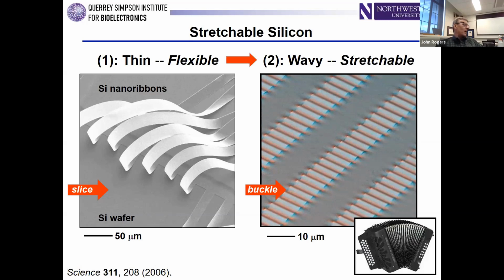Still silicon, it still offers the same electronic properties, can be thick enough to support the kind of transport characteristics that you need for a MOSFET, for example, but very, very flexible because of the extreme thin geometry. So maybe 100 nanometers in thickness might be a typical number compared to the millimeter thickness of the wafer. You're talking about 13, 14 orders of magnitude reduction in bending stiffness. And so that has a qualitative impact on the way you think about the material.